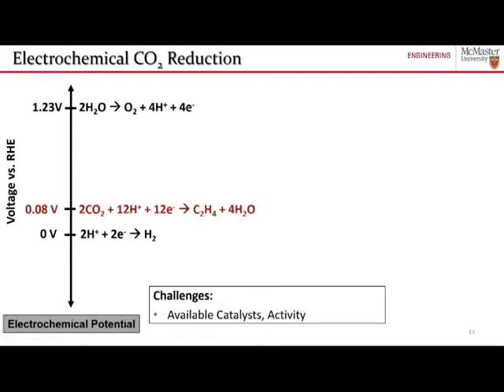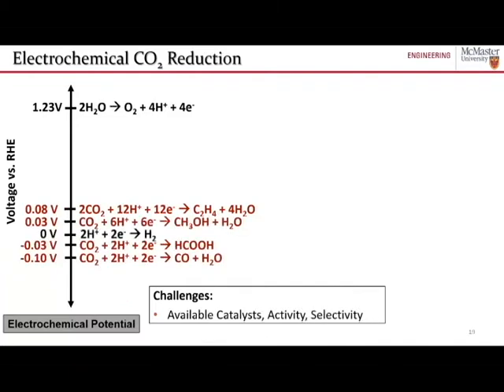Now I show here the thermodynamic reversible potential for carbon dioxide conversion into ethylene. So thermodynamically, at any electrode potential below 0.08 volts versus the RHE scale, we can thermodynamically make ethylene from carbon dioxide. But realistically, experimentally when we measure it, this reaction can't occur until about 800 millivolts lower than 0.08 volts versus the RHE, which means that we're having 800 millivolts of energy loss during this process. So clearly the activity of catalyst is not where we need it to be in terms of the energy conversion efficiencies.